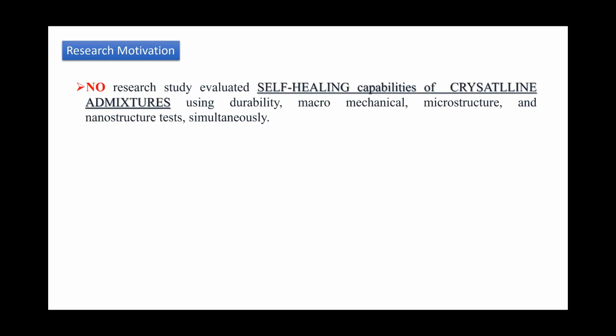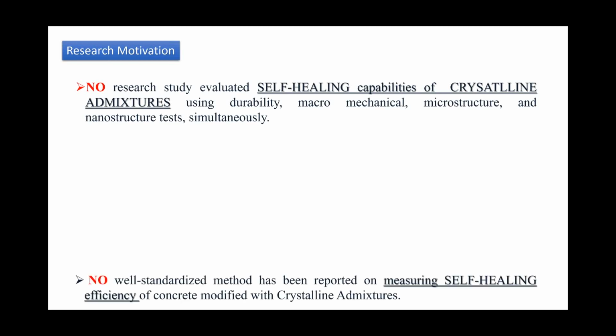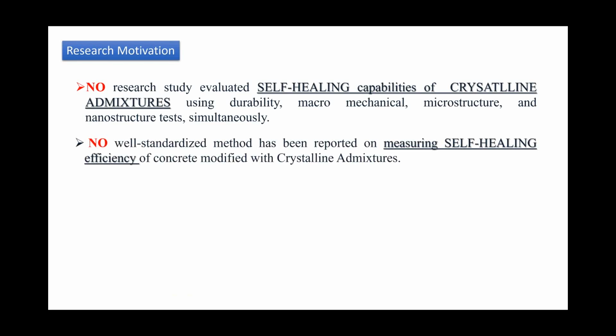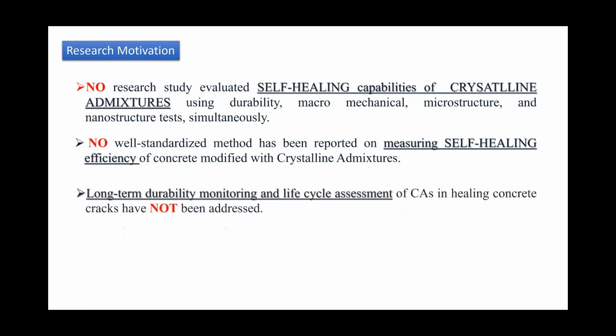So as part of my research, as I mentioned earlier, I'm using these kinds of admixtures, but there are still so many unknown questions. One of them is, I couldn't find a research study that evaluates the self-healing capabilities of this admixture using durability, macromechanical, microstructure, and nanostructure tests simultaneously. And also, I couldn't find any well-standardized method that has been reported on how we can measure the efficiency of concrete when it's modified with this crystalline admixture. Also, long-term durability monitoring and life cycle assessment of this admixture is somewhat lacking, and it hasn't been addressed so far.